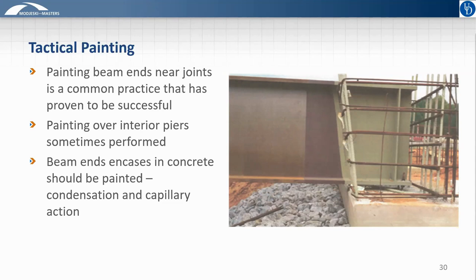And so the process goes something like this. At night, everything tends to cool down, including the concrete. And then when the day starts and everything starts to warm up, including the air, the humidity of the air increases. The concrete still remains relatively cool, steel being a very excellent thermal conductor, so the area of the concrete will also remain cool. So you have warm, humid air against cold steel, and that's what leads to condensation of moisture onto the steel,